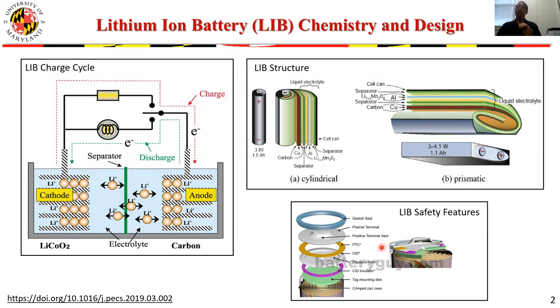They are not effective, unfortunately, against other triggers. There are a number of other possibilities by which thermal runaway in a lithium-ion battery can be triggered. For example, an internal short circuit might happen for a whole spectrum of reasons. Disconnecting the cell from the external electrical circuit will not help to stop that. It doesn't protect against impact, and it doesn't protect against heating of the battery by an external source. So all these things can actually result in failure of the battery.